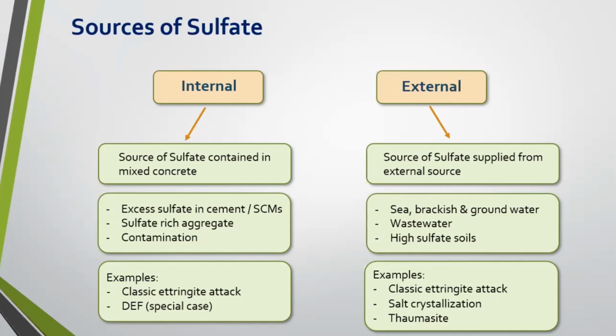Sulfate-rich aggregates, obviously. And then you can get contamination from other sources. So it may be something that you're adding to your concrete mix that in small volumes is not problematic at all, but if it's adding to an overall concentration of sulfates could potentially be problematic. Classic ettringite attack that we've talked briefly about. And then I've got a special case listed here at the bottom of DEF. Now, DEF is what's called delayed ettringite formation. And where you would typically see DEF is in cases where you've got very high initial curing temperatures in excess of 158 degrees Fahrenheit. So obviously mass concrete would immediately come to mind where you're generating high temperatures from hydration.